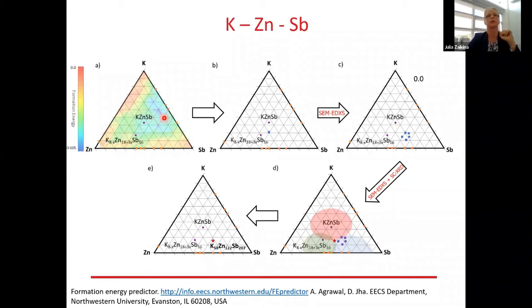So for instance, the low formation energy suggests that there might be a stable ternary compound found here as well as in this area. So we tried the composition over here, and indeed there was an indication of a new phase with a very complex crystal structure. So we did some compositional screening, trying different compositions until we figured out the composition of the phase, also using SEM-EDX. And so this allowed discovery of that very complex compound, potassium 58 zinc 122 antimony 207. So very complex composition and structure.